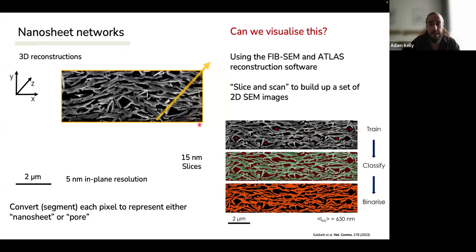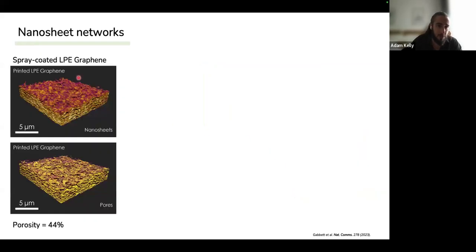You can take ImageJ, for example, and you can train ImageJ to tell what is a pore, so what is not a nanosheet and what is a nanosheet. And then by creating these images that are binarized into simply nanosheets and simply pores, we can reconstruct the network by building up all of these images. So this is a network here of just the nanosheets with the pores removed, and this is just the pores in the network. And what we find is that the porosity is huge. It's about 44%, and every one of these pores here is connected. So this is one big macro pore basically inside of the network. And this is good for something like batteries, for example, where you have an electrolyte and you want it to be able to penetrate and access all parts of your network.